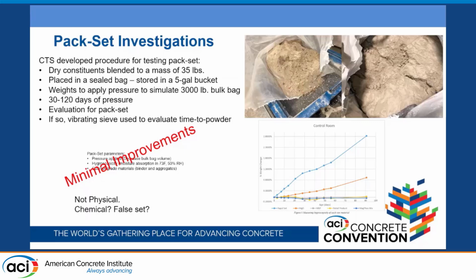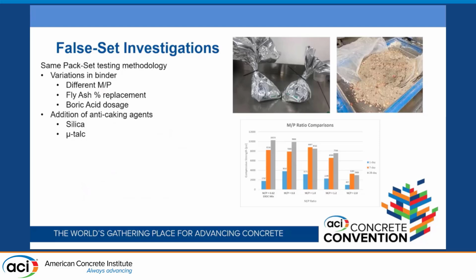And so if it's not physical, then it's chemical. What's going on? So back to the drawing board. Now we went from a pack set investigation to a false set investigation. It's the same pack set testing methodology, but they started removing pieces of the binder one at a time to see what it was. They varied the M to P ratio, the fly ash replacement percentage, the boric acid dosage. They also tried the addition of anti-caking agents like silica or micro talc. And the result was that reducing the boric acid dosage alleviated the pack set. Well, that's a problem because we need that boric acid for our set time.